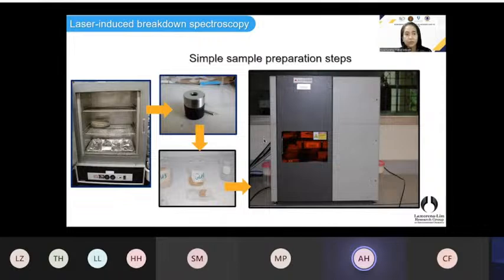So we just dry our soil samples or sediment samples and then sieve it in a particular particle size range, and place it in a molder, and then prepare it as compact pellets. And then once we've prepared these pellets, we place them inside the stage of this equipment. And we use laser to irradiate the samples. And after several seconds, we can get a spectra of our sample. We can analyze many elements of interest using this equipment.